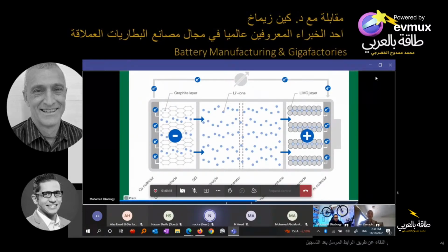And a separator is usually microporous, meaning little tiny, tortuous holes in plastic. Why plastic? It's usually polyethylene or polypropylene. It's plastic because that electrically isolates the cathode from the anode. So you have a cathode, a separator, and an anode. You can squeeze those together and the cathode doesn't short circuit to the anode.